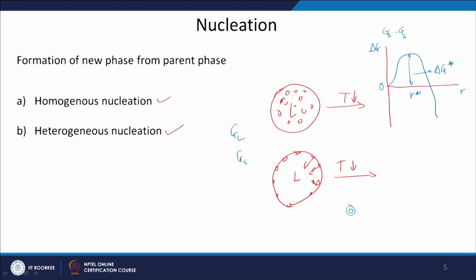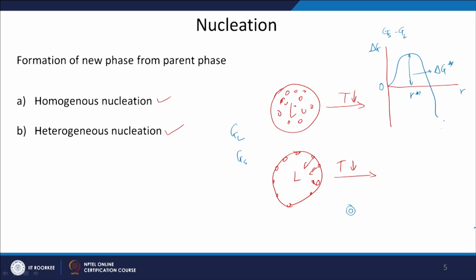Earlier also we used this term. This is the activation barrier for formation of new phase from the old phase. So, this much activation barrier you have to cross to go into the next phase or to have the transformation. And at this point the radius of the nuclei will be equal to R star. If my radius of the nuclei is below R star, then I will call it an embryo. That means it is not a stable nuclei, it can again go back into liquid phase. If it crosses this critical radius R star, then it will become a stable nuclei, and then the free energy will start coming down, and then it will become negative later on. This is how the change in the free energy is there when we transform from one solid to another solid, one phase to another phase.